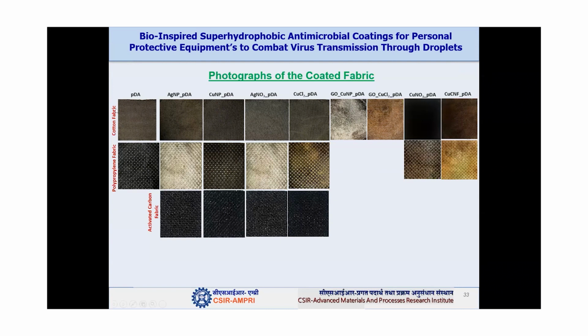You can see the cotton fabric, which is very common for masks. Polypropylene fabric, again, is a very common and popular material for mask fabrication. And this is the activated carbon fabric. All 3 fabrics have high utility in personal protective equipment, and we have tried to design the coatings on these fabrics. You can see in some cases, particularly copper nanoparticle and copper nitrate, we got very uniform coatings on the different kinds of fabrics. Even with copper nanoparticle on polypropylene, we got a very beautiful coating.